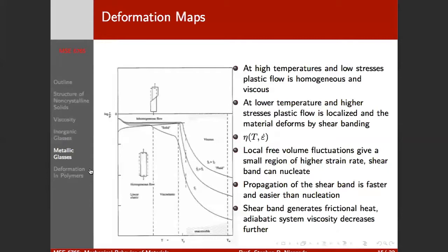They'll become even less viscous, right? In reality, our glass isn't strictly shear thinning like that, but we have plastic dissipation, right? So what are we doing? We're generating heat, and the viscosity is a function of temperature, right? So we have regions where our viscosity drops very quickly during the deformation, right?